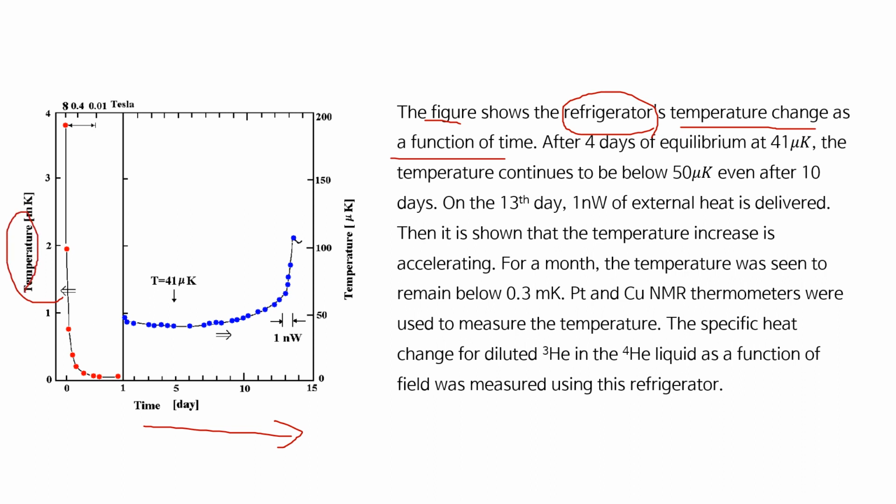After 4 days, the temperature reaches the lowest temperature, 41 microkelvin, and this temperature continues to be below 50 microkelvin even after 10 days.